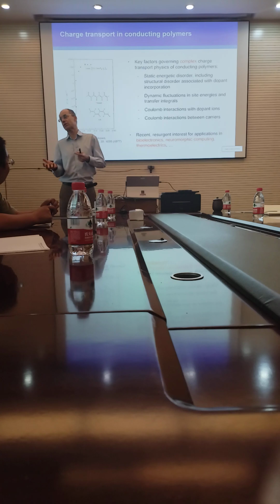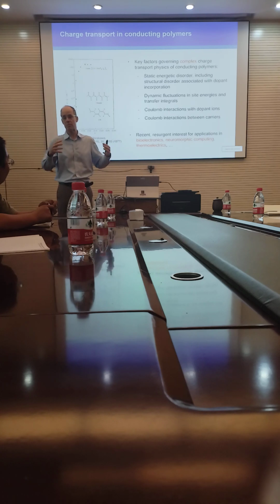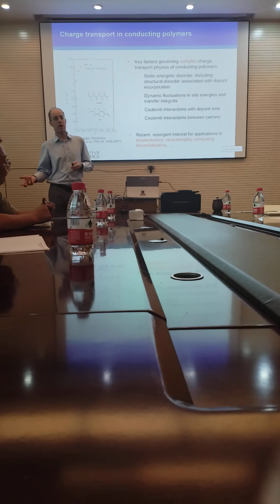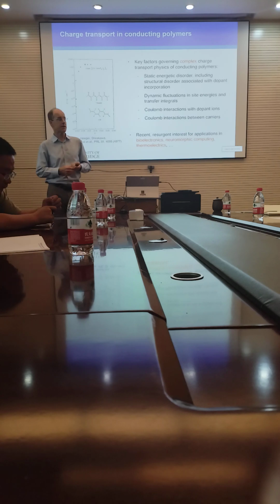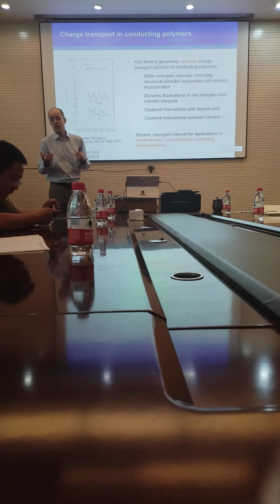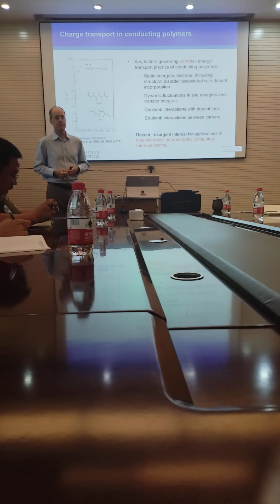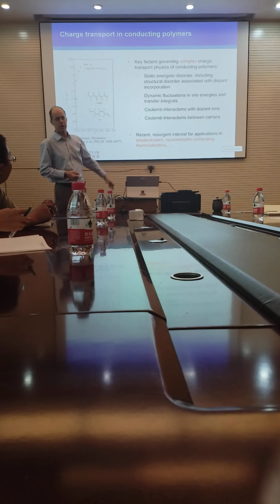The electronic charges interact with the dopant counterions. There's an attractive Coulomb interaction between the holes on the polymer, if it's p-type doped, and the negative counterions that stabilize that electronic charge. And then you also need to take into account the electron-electron interaction between the carriers. And so that makes it really complicated.